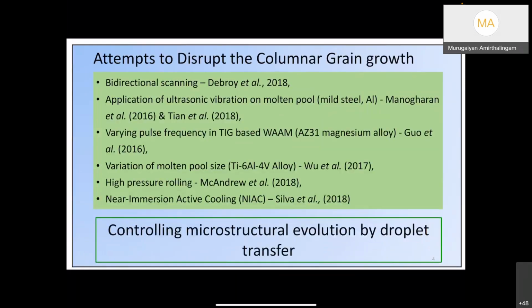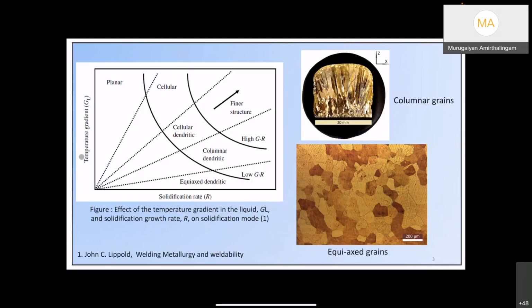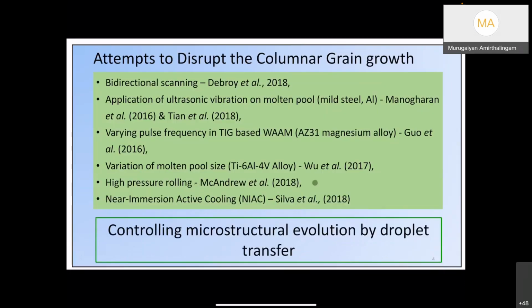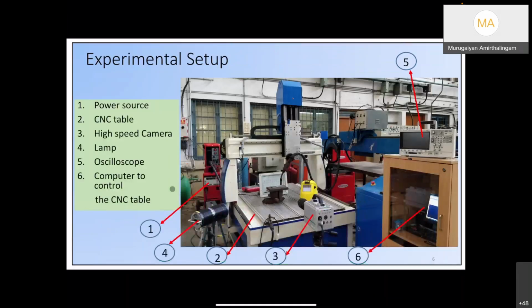Once we carefully manage the temperature gradients at the solidifying melt pool, we know that we can convert from planar to equiaxed microstructure. People have attempted several methods, like changing the scanning strategies or introducing vibrations so that we introduce more nucleation, or various methods to manipulate the temperature gradient. But I'm going to tell you one neat technique, how we have done it and how it can be done, and people are adopting this technique as well.